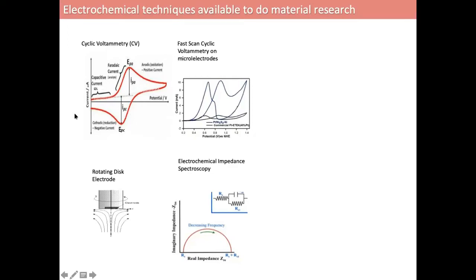Most of you must have heard about this technique, and I'm going to talk more about it. Here we apply the potential and measure the current response across the electrode-electrolyte interface. Normally in cyclic voltammetry, we measure at a scan rate of about 0.1 volt or 100 millivolt per second. Okay, but you can in fact do the same measurements at very high scan rate. It is called fast scan cyclic voltammetry.